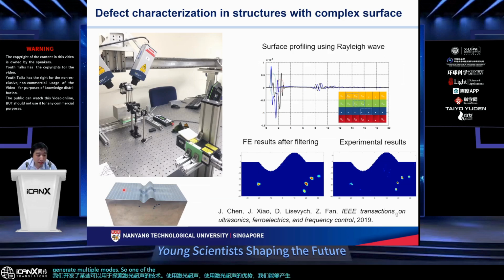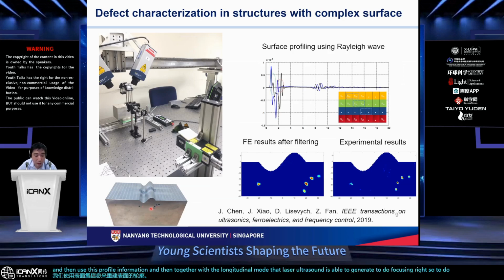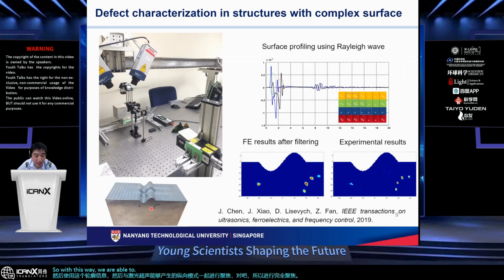So one of the laser modes, the generated ultrasonic mode, is a surface wave that will be able to crawl around the surface of the structures. Then we use this surface crawling information to reconstruct the profile of the surface, and then use this profile information together with a longitudinal mode that laser ultrasound is able to generate to do focusing, right? So to do total focusing. In this way, we are able to reconstruct defects in a complex surface. Okay, so that's one of the works that we have done.